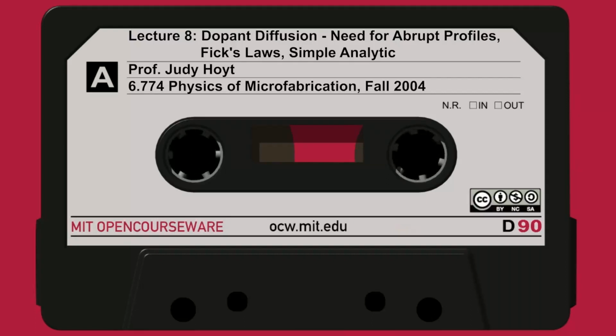So to compensate for that and have the resistance go down, we really need to up the doping concentration. And there's a fundamental physical limit on how much dopant we can put in the silicon and how much of it will be electrically active. So this is becoming a real problem. We need to find new ways to activate dopants to higher levels if we're going to be able to manage this design trade-off.